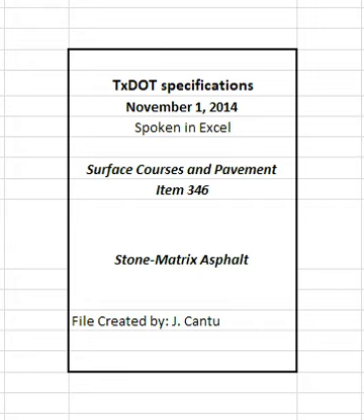4.9.3.3.3.2 Record tests. Perform a joint density evaluation for each sublot at each pavement edge that is or will become a longitudinal joint. Joint density evaluations are not applicable in areas described in Section 346.4.9.3.1.4, miscellaneous areas. Determine the joint density in accordance with Tex-207-F, Part 7. Record the joint density information and submit results on department forms to the engineer. The evaluation is considered failing if the joint density is more than 3.0 pcf below the density taken at the core random sample location and the correlated joint density is less than 90%.